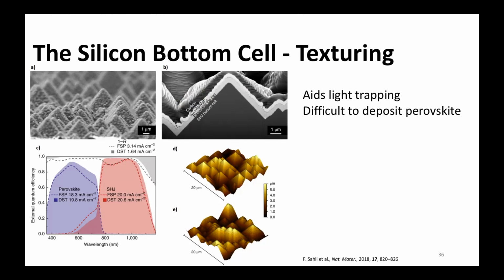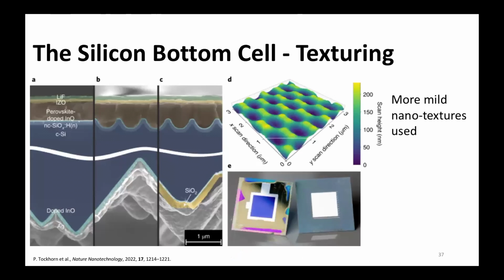Another thing is the texturing. So it's pyramid. It can be pretty big, but it can also be pretty small. You can imagine that if you have a textured top of silicon, it's very difficult to deposit the perovskite. So if you want to do spin coating on a bumpy surface, it's not that easy. So maybe you have to do other tricks, evaporation, but you can also play with the texturing.